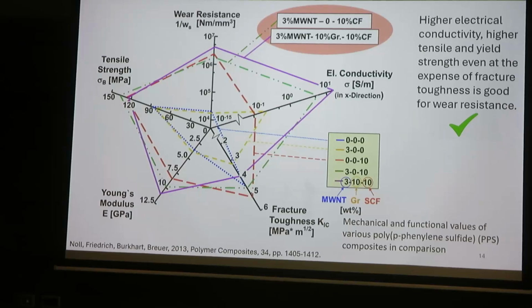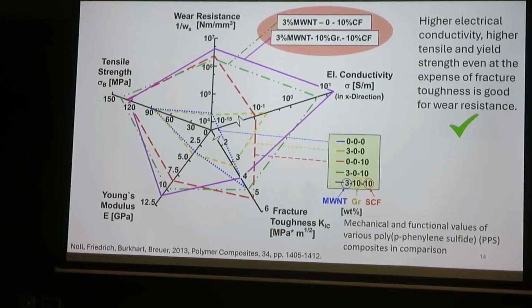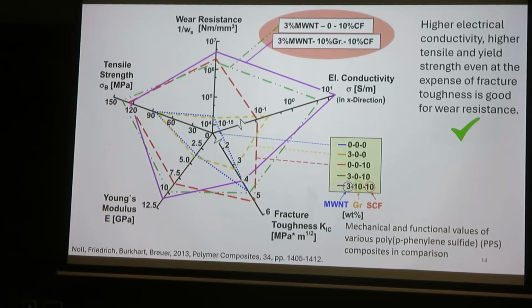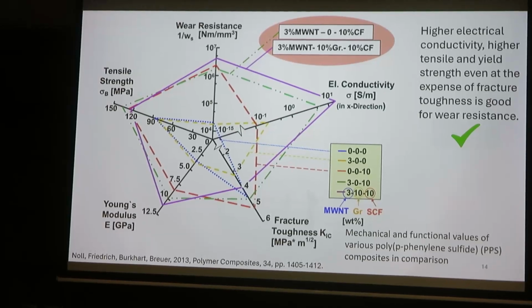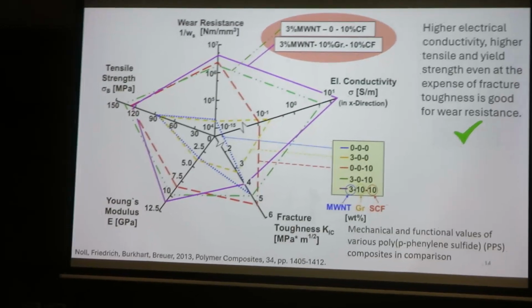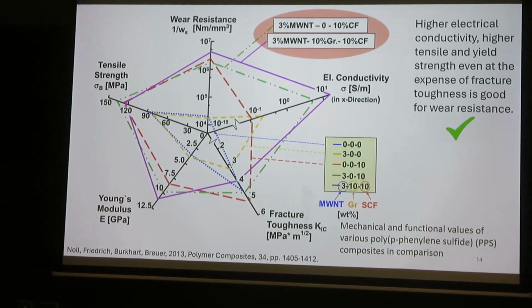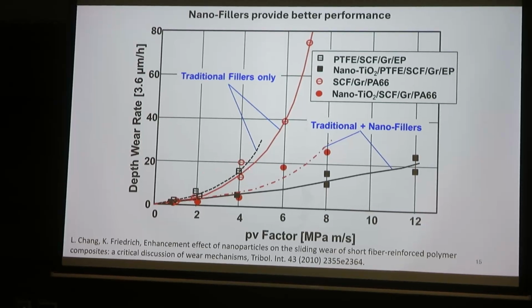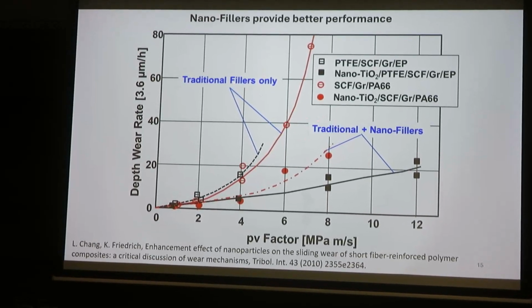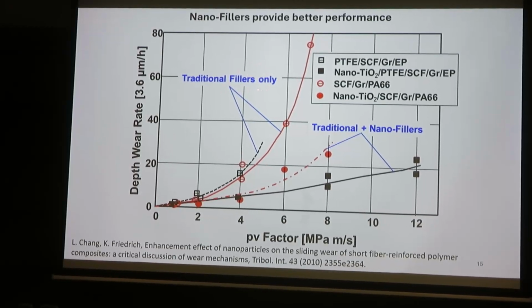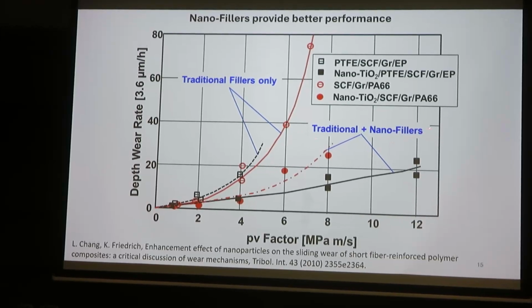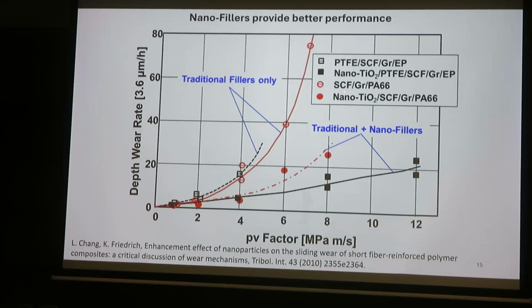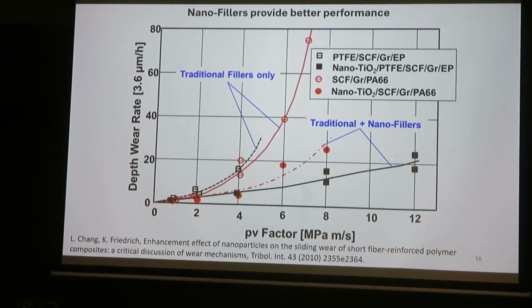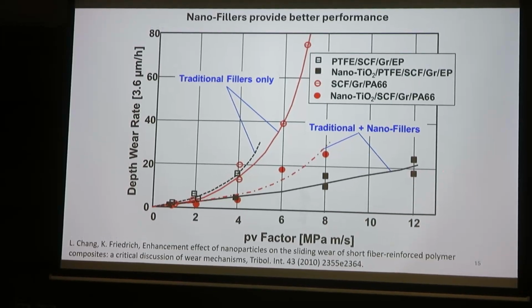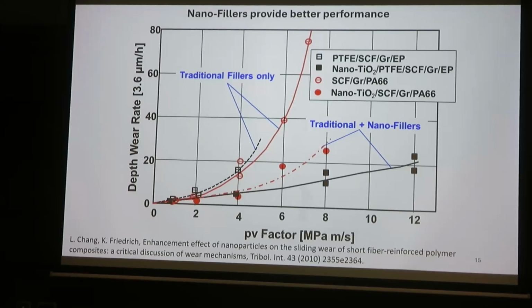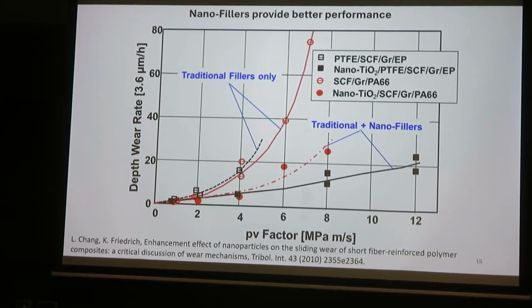Okay. So when we are looking at designing a polymer composite, perhaps we have to get this kind of idea, this kind of concept, where we enhance the strength, but also think about enhancing the thermal conductivity of the composite. In this one, they have shown traditional fillers, which include short fibers or long fibers, compared to nano fillers, where we have nano TiO2. Nano fillers tend to give better results. One reason is they can make the material more thermally conducting, and another is they have a polishing effect on the counterface.